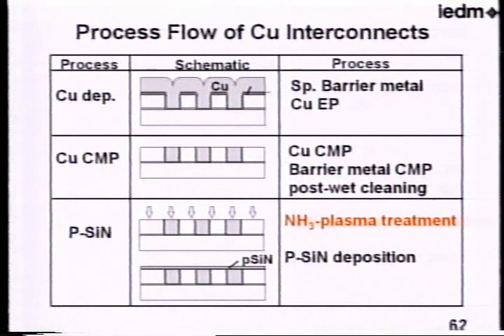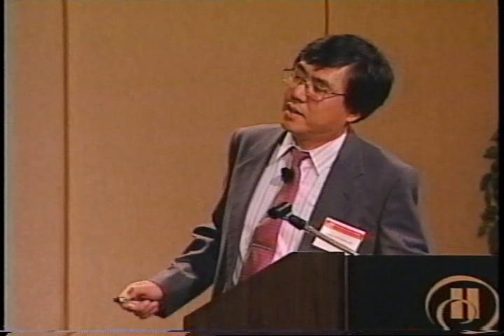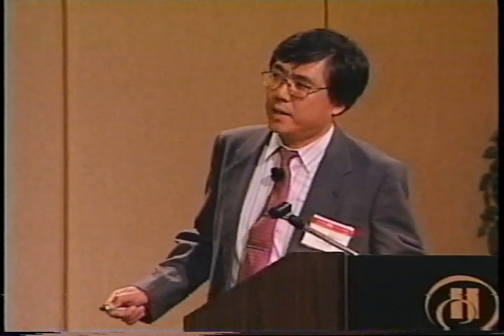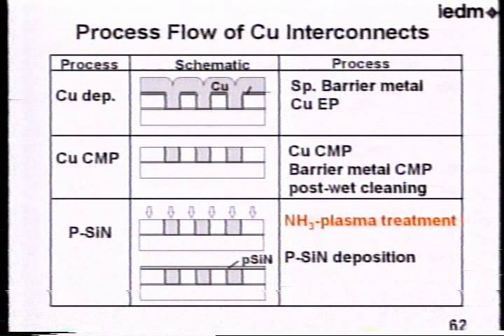For example, this TDDB lifetime is strongly dependent on process condition like this. For example, this is a process of copper interconnect, copper deposition, followed by a copper CMP. Then we conventionally do some plasma treatment to make a good adhesion between a capping layer and ILD. We typically use an ammonia plasma treatment. This removes some contamination on ILD and also reduces the copper oxide surface.